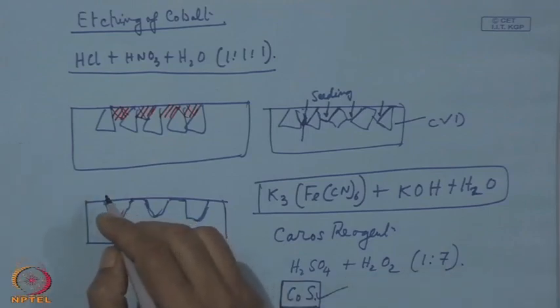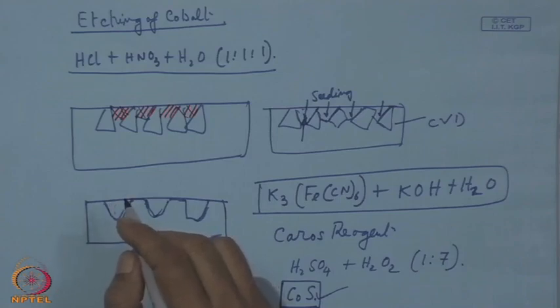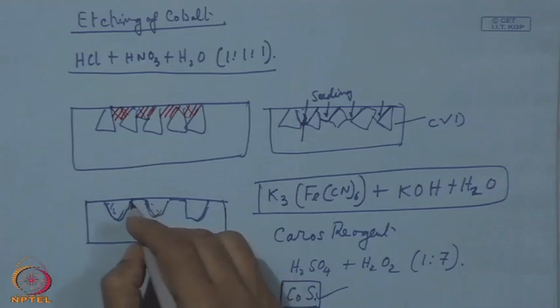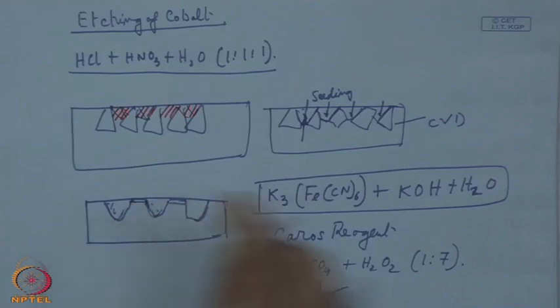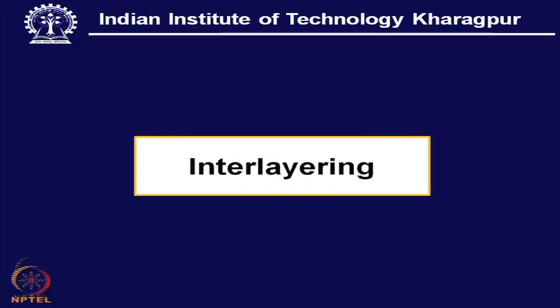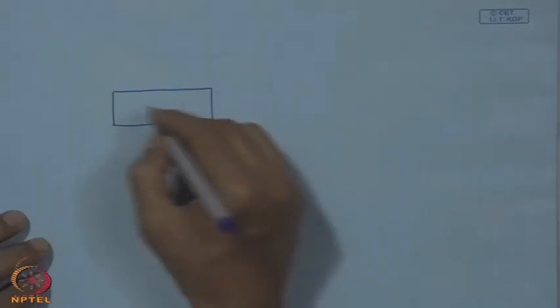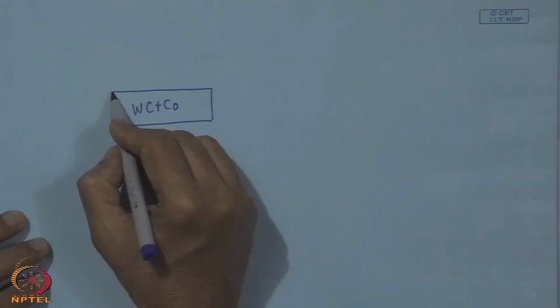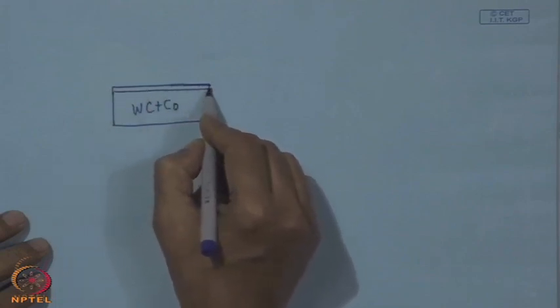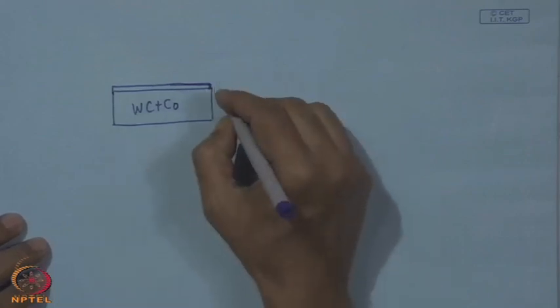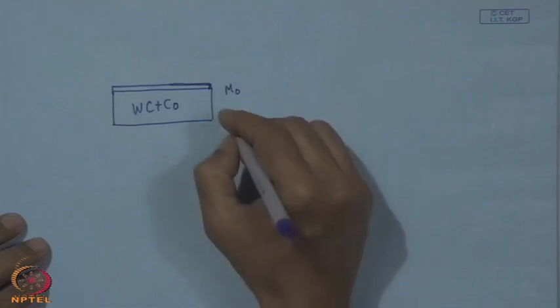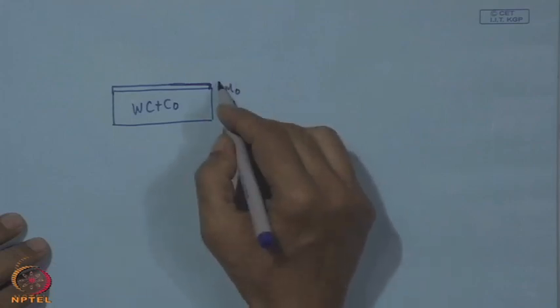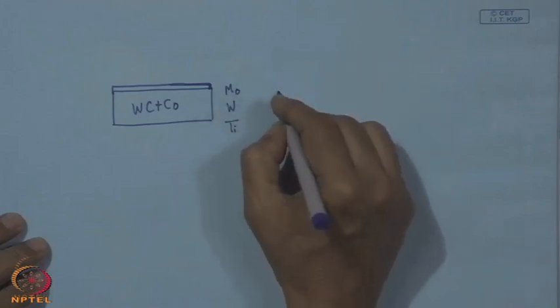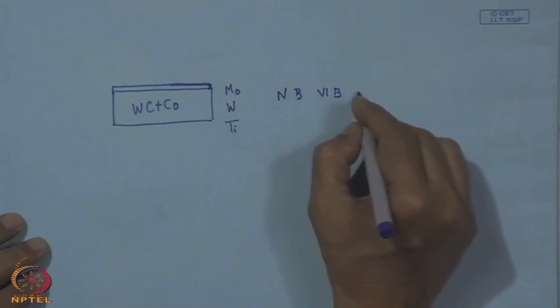So, now here what we see is seeding, and this seeding is done in this pocket with total passivation of this layer. There are various processes which have been successfully attempted, and this is one of those: interlayering. Interlayering means, even if we have tungsten carbide plus cobalt, we can suppress any adverse action of this cobalt by interlayering with a metal, say for example, molybdenum or tungsten or titanium. These are mostly found from group 4B, 5B and 6B.